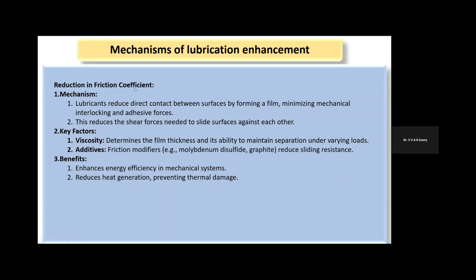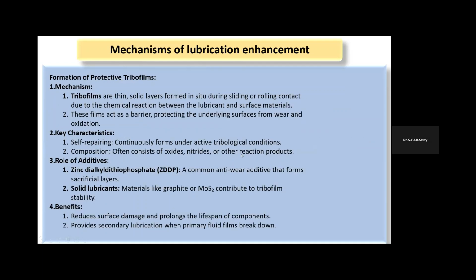So we have a reduction in the friction coefficients. Lubricants reduce the direct contact between the surfaces by forming a film, minimizing the mechanical interlocking and adhesive forces, and this reduces the shear force needed to slide the surfaces against each other. The key factors in lubricants, we know, are viscosity and the use of additives, especially friction modifiers, which can reduce the sliding resistance. Then formation of protective tribofilms in the lubricating application.